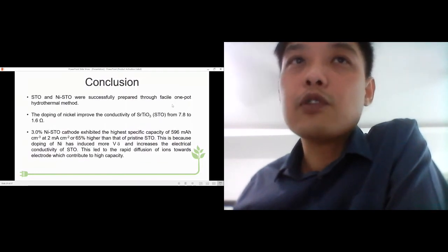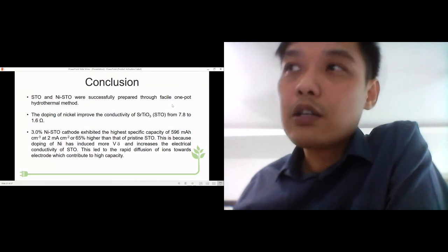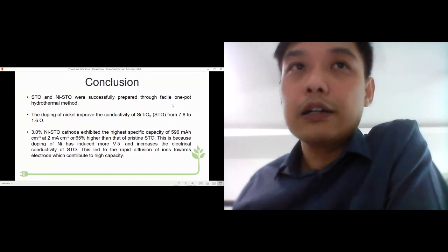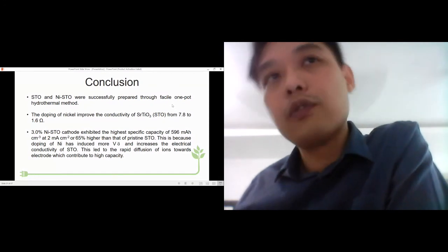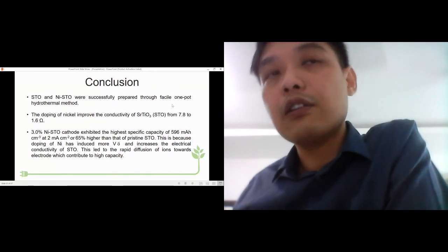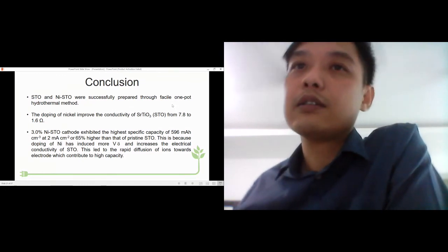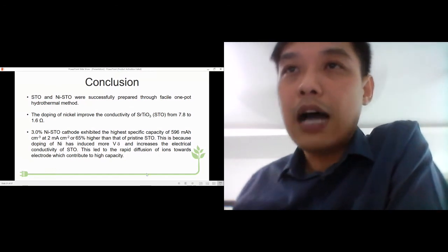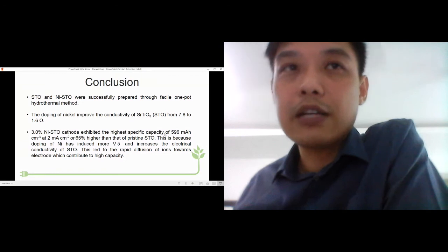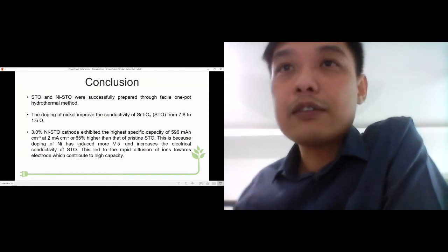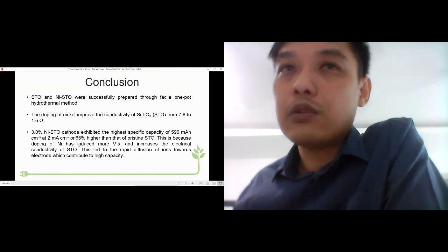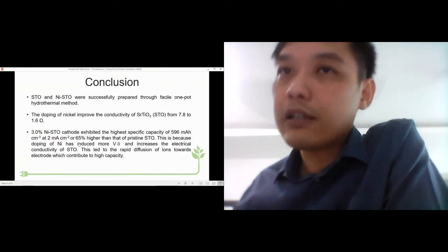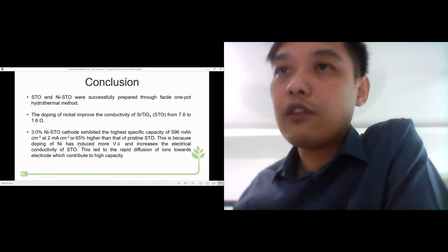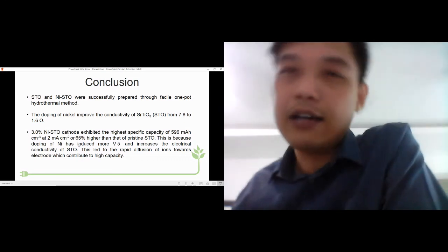We successfully prepare it with very simple methods, so it's easily scalable. Definitely the nickel itself has improved the resistance and conductivity. We have reduced the resistance and increased the conductivity. On top of that, this also exhibits high specific capacity, about 600, and 65% higher than the previous STO. This is because the doping has induced more oxygen vacancy and increased the electric conductivity of STO. This leads to a rapid diffusion of ions toward the electrode, which contributes to the high capacity.